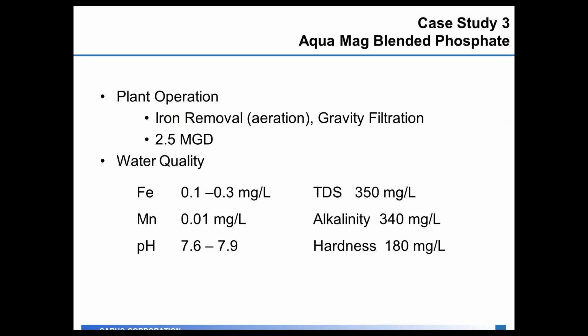The treatment plant was iron removal with aeration and then gravity filtration, and they treated 2.5 mgd. If you look at their water quality, they only had about 0.1 to 0.3 milligrams per liter of iron going out the door, so just barely below the secondary maximum contaminant level, which leads you to tell that the corrosion and the red water issues were coming from corrosion of the distribution piping. Manganese was 0.01 milligrams per liter. The pH fell in the range of 7.6 to 7.9, and the hardness was 180 milligrams per liter.